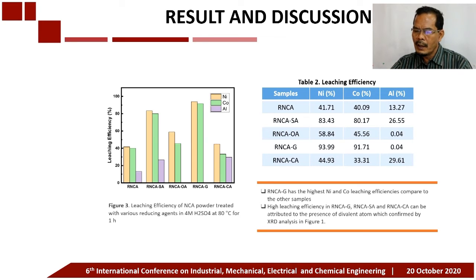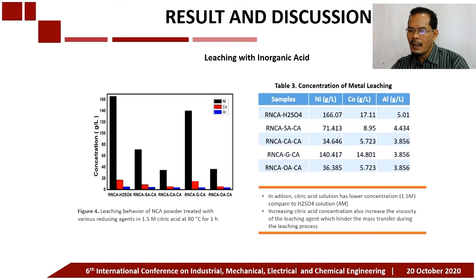Spent NCA with glucose as a reducing agent has the highest nickel and cobalt leaching efficiency compared to the other samples. The high leaching efficiency in NCA glucose, NCA stearic acid, and NCA citric acid can be attributed to the presence of divalent atoms, which was confirmed by XRD analysis in figure 1. Here, NCA leached using organic acid, citric acid, gives lower metal leached in comparison with the NCA leached with sulfuric acid.